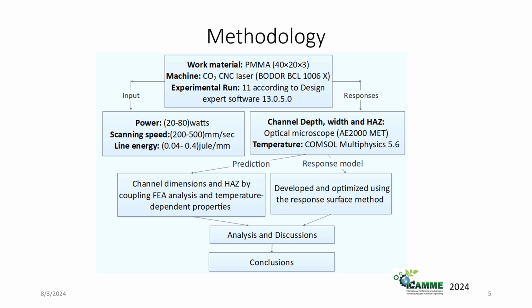The methodology is shown in this slide, where a carbon dioxide CNC laser is used to create microchannels on a PMMA workpiece, with power varied from 20 to 80 watt, and scanning speed from 200 to 500 millimeter per second. According to Design Expert software, we get 11 experimental runs. Each PMMA workpiece, having dimensions of 40 by 20 by 3, was machined using a single pass. The responses, channel depth, width, and heat affected zone, were measured using an optical microscope, and the temperature generated on the work surface was estimated using COMSOL Multiphysics software.